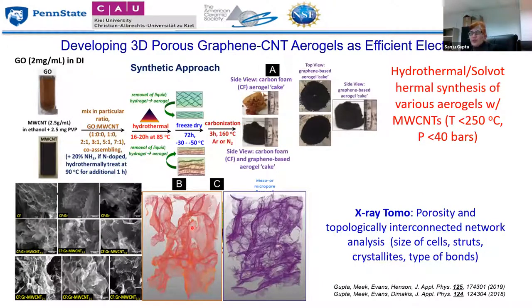So for this particular application, what we did here, we developed what we call the three-dimensional mesoporous graphene carbon nanotube aerogels. And as you can see here, this is the classic, very simple, but looks complicated, but it's a very straightforward hydrothermal synthetic approach where we have a graphene oxide and we have a functionalized multi-wall carbon nanotube depending upon the ratio. And so we studied the whole range.